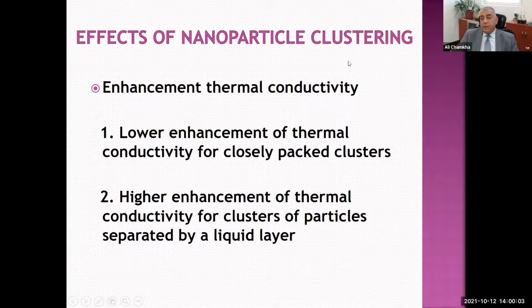The effect of nanoparticle clustering. As I said before, the beauty of nanofluids is that the nanoparticles are suspended in the base fluid at all times. This is when you get the most effect of nanoparticles. Lower enhancement of thermal conductivity for closely packed clusters. Agglomeration is a problem, when they agglomerate together. High enhancement of thermal conductivity for clusters of particles separated by a liquid layer is better for that.